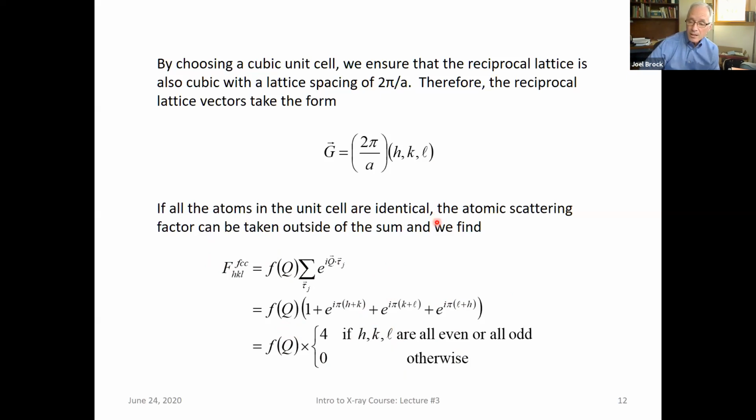So you don't really have to worry about which unit cell you pick, about it being the smallest possible, because the structure factor will actually zero out those extra Bragg peaks for you. And the computational simplicity of working with a cubic rather than a rhombohedral unit cell is significant.